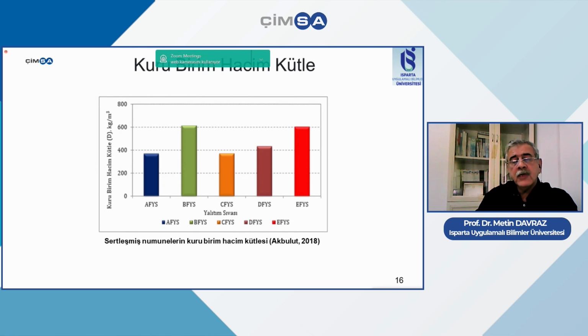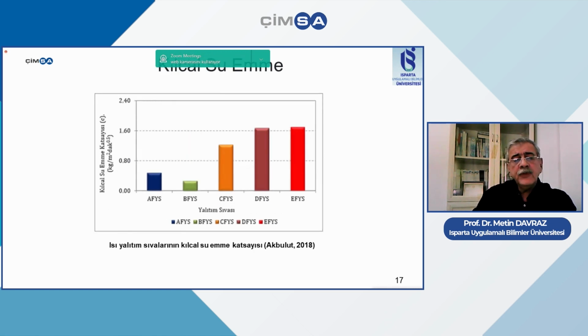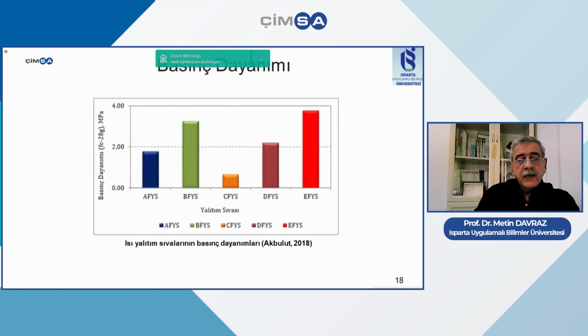And the appropriate samples have been here researched, and you can see here 2 out of 5 samples are below the value, while the other 3 are actually above the 400 value. And here, again, you can see here the water absorption coefficient here for insulation plaster, 5 samples. And you can see the results. And see here, 3 of them are above the 0.8 level.